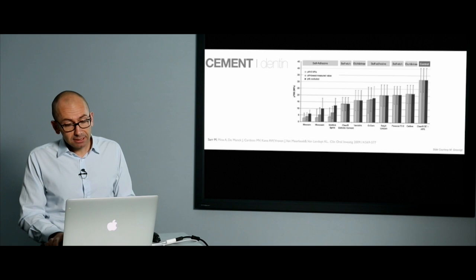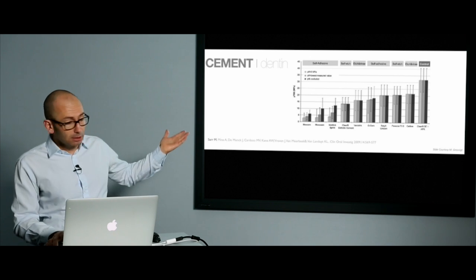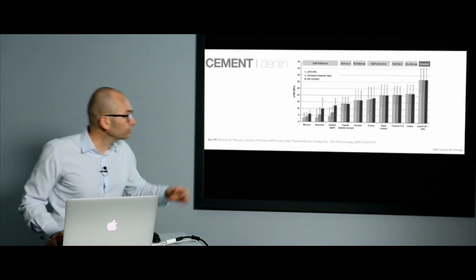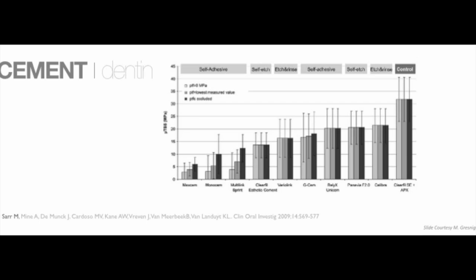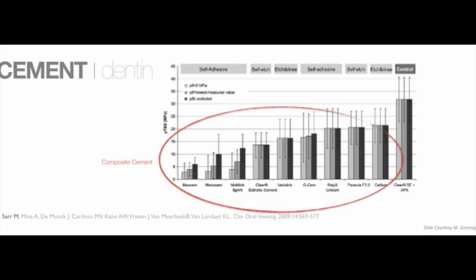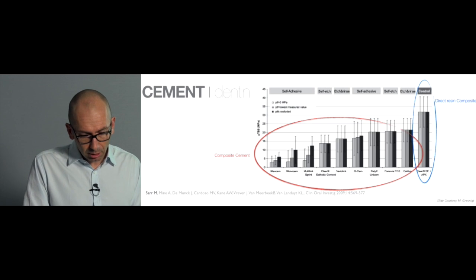And if we look at this study, which is very interesting, you've got a lot of different brands, and the topic here is not to say, okay, you don't choose the G-CEM, choose maybe the G-CEM because the values are better. It's absolutely not about this. The point is that all those different brands, all those different families with the self-etch, the self-adhesive, the etch and rinse, all those composite cements, they just show us values which are not that good compared with the direct composite one. So just keep in mind that the control in the study is the gold standard. We want to have the strongest values. So why not choose the classical direct composite that we already have in the office? Why do we have to buy a new one specifically to bond ceramic veneers? Keep that in mind, and we will come back to this topic later on.